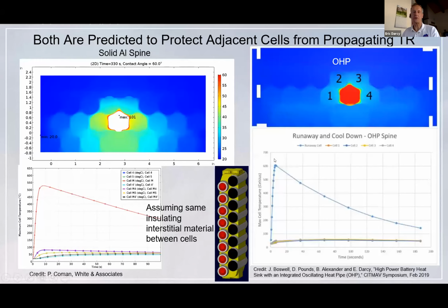The thermal runaway cell reaches up to 600+ degrees, but the adjacent cells are protected. They are kept below 100 degrees Celsius, and that's the name of the game here. And this is with 2 millimeter spacing and our ceramic putty as the interstitial material. Most of the heat is shunted into the spine, or the oscillating heat sink spine.